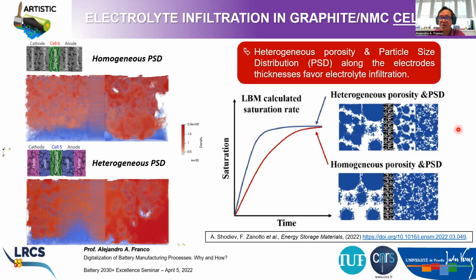So if you have an electrode with a bilayer structure, where you can tune the porosity and the particle size distribution, so you use maybe smaller particles in one layer and bigger in the other layer, or bigger pores in one layer and smaller in the other layer, you can speed up the saturation of your cell sandwich. You can basically accelerate the electrolyte infiltration of your cell. We believe this work is interesting because it can pave the way towards a computational screening of the influence of electrode microstructures on the wettability of lithium-ion battery cells.